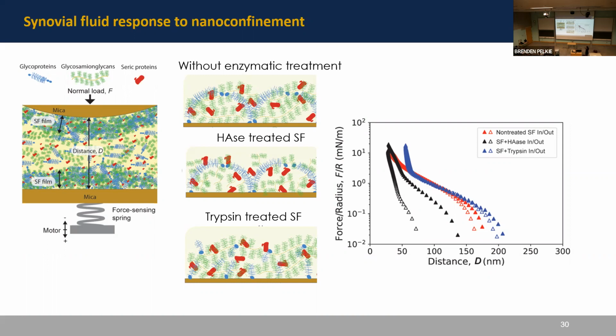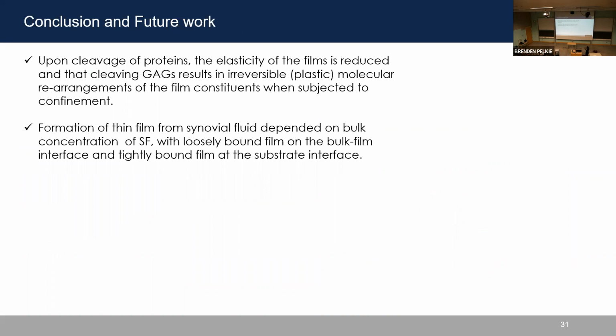So this means that there is loss of energy and irreversible molecular rearrangement because of the cleavage of the hyaluronic acid. So these experiments helped us to figure out that there are different roles of the synovial fluid components that change the integrity of the synovial fluid film that is formed at articular cartilage. For example, upon cleavage of the protein, the elasticity of the film is reduced, and the cleaving of the glycans resulted in irreversible molecular rearrangement. And we also saw that the retention of the thin film from the synovial fluid is dependent on its bulk concentration, and there is a loosely bound outer layer that can be easily washed off in the washing step.